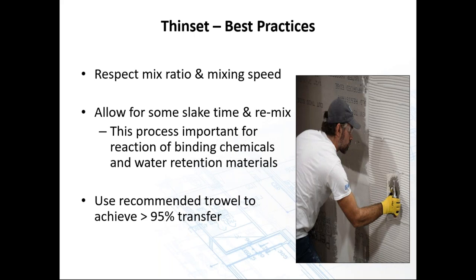Use the recommended trowel to achieve 95% transfer. Take note of that picture of the gentleman installing mortar right there. You notice how he's combing the mortar in one direction, keeping all of the lines going the same way. That piece of tile or stone that he's going to pick up and back butter, he puts the ridges going the same direction. So as he places that together, puts it into the mortar, he'll slide it up and down perpendicular to those ridges, achieving that full coverage, that 95% transfer, making sure that that tile or stone is properly locked into place and no problems with it.